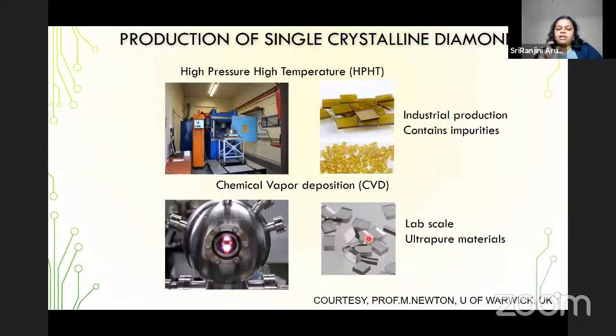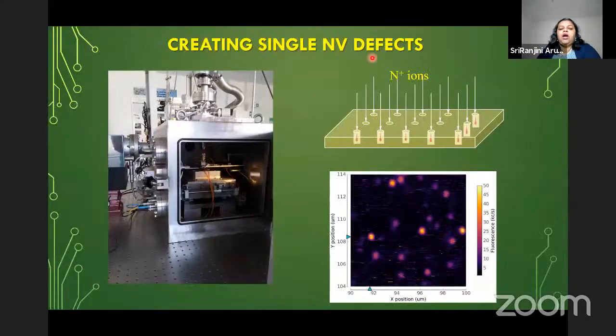Once we have the ultra pure diamond substrate, the next stage is to make the NV defects. How do we do it? We take it into the plasma chamber, and this is the diamond lattice, and we impinge it with ionized nitrogen gas, and then we try to knock out one of the carbons. If you image that, we can find that all the bright spots are where the carbon is replaced with a nitrogen. This is the image, or the signature, of the nitrogen containing diamonds.